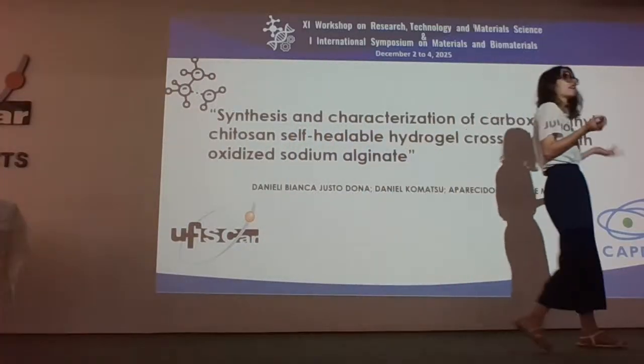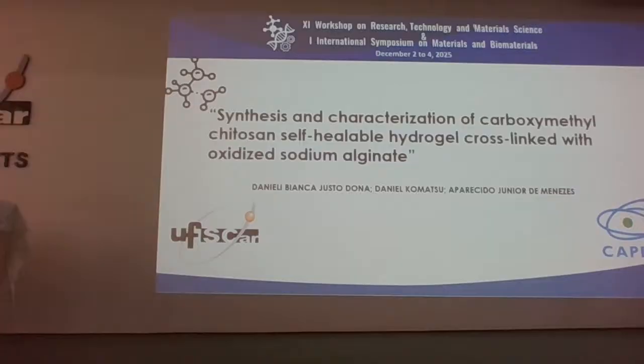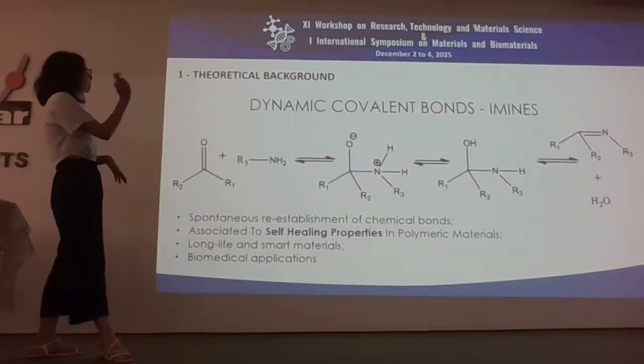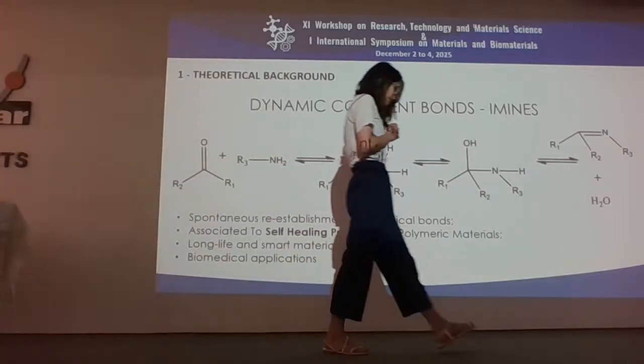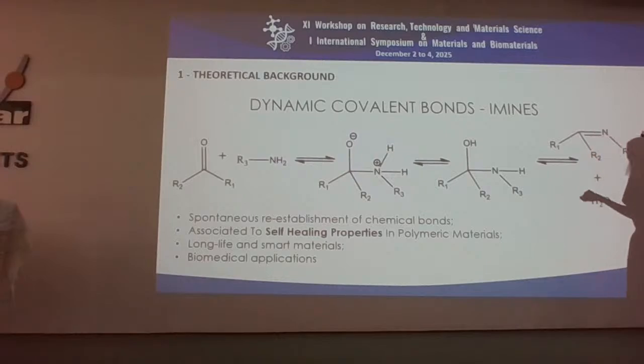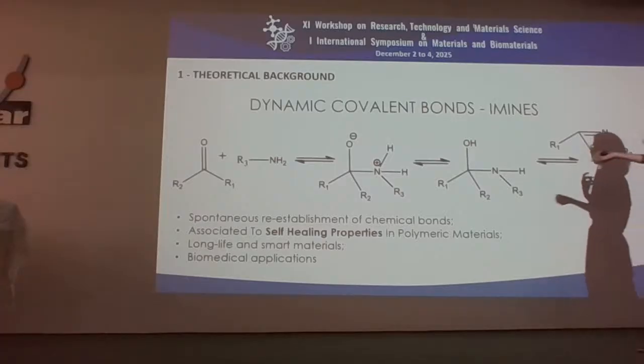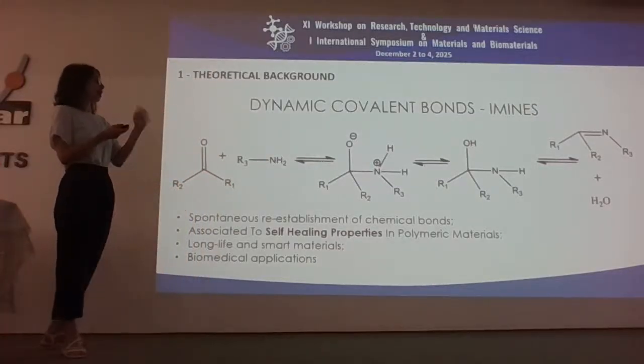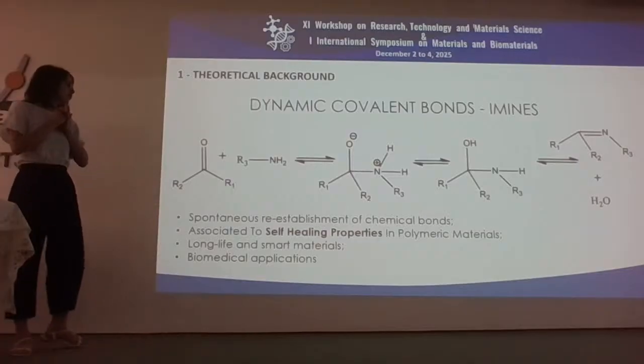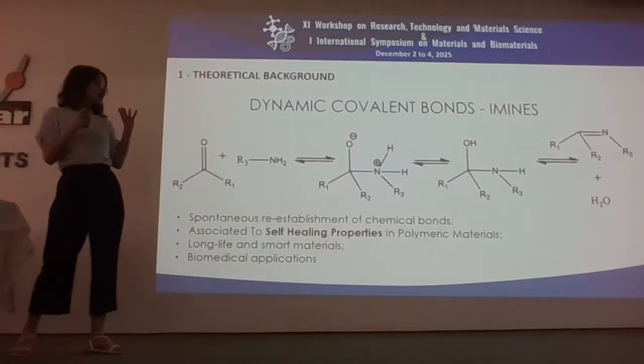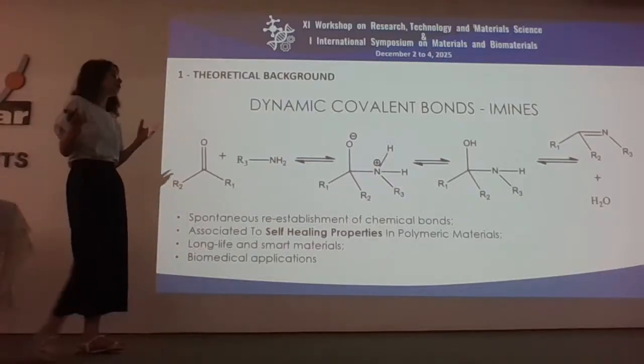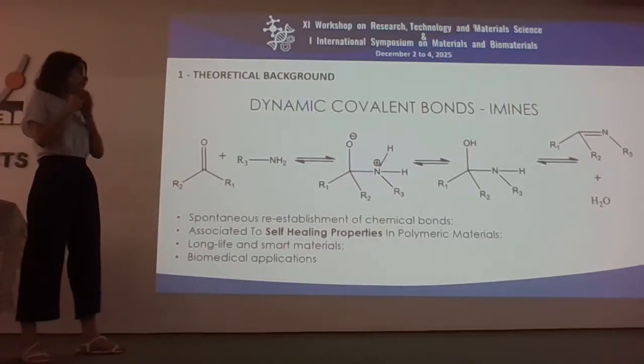The main difference between a regular hydrogel and a self-healable material is that when the self-healable suffers any physical damage, it can reassemble its structure. This property relies on the theoretical background of the dynamic covalent bonds. We chose to use amine and aldehyde groups to form imine groups that have this property of reassembling the structure. So when we combine these 2 materials, amine and aldehydes, we can have a spontaneous reestablishment of the chemical bonds. And this reestablishment will give the material the property of being organized together again.